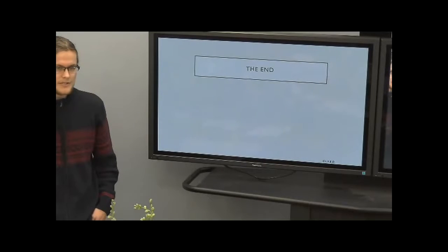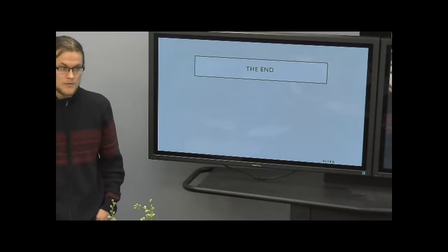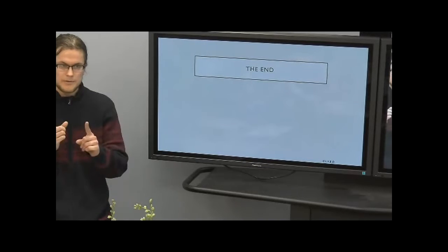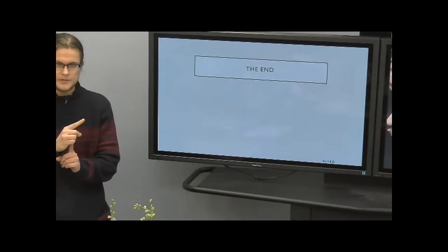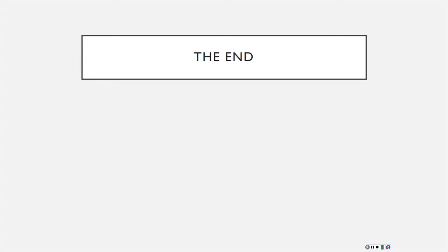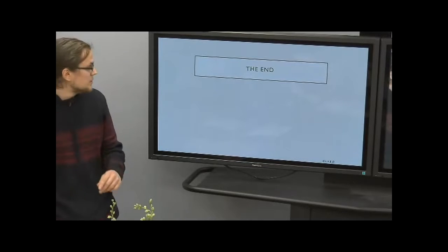The literature I've seen is that the perovskite can act by itself to separate charges. It has an internal electric field, but that's for methyl ammonium, which, with the internal cation, can create internal electric fields. But for cesium, it's just a charge. Oh, and yours was not lead, it was cesium? It's lead, but it's cesium.